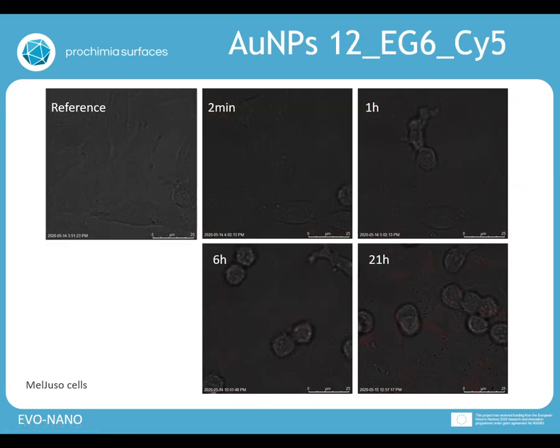However, in the case of the gold nanoparticles with the 12.5 nanometer size of the metallic gold, we have observed the quenching of the fluorescence activity of the CY5 dye, and we suspected that the fluorescent activity of these gold nanoparticles is quenched by the metallic gold.